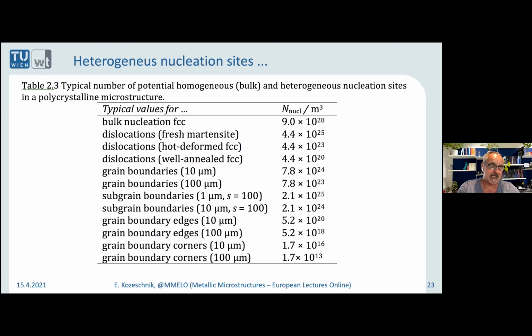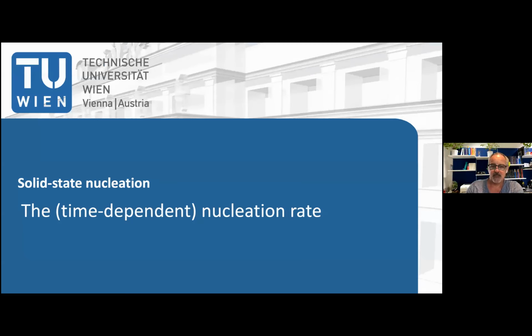And just to give you an example, grain boundary corners will be very prominent nucleation sites if you form ferrite from an austenitic matrix. So when austenite decomposes into ferrite, many times the grain boundary corners will be the prominent sites. So the metallic microstructure will definitely impact nucleation of particles by simply providing a various number of potential nucleation sites.